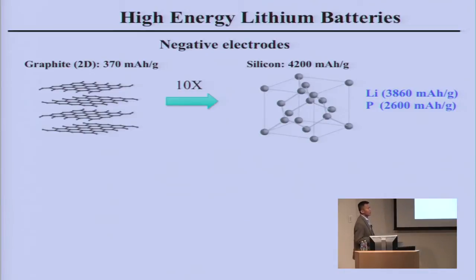To get down to low cost, the most powerful knob you can tune is actually energy density. If your manufacturing cost and material cost are the same, and your energy density becomes 3 times, your cost becomes 1/3 for the same battery capacity. For the negative electrode, we have been using graphite for 20-something years now. We want to go up to 10x, so silicon is possible. And lithium and phosphorus also store a lot of lithium, with 10 times higher capacity.